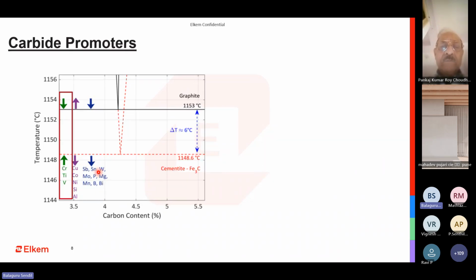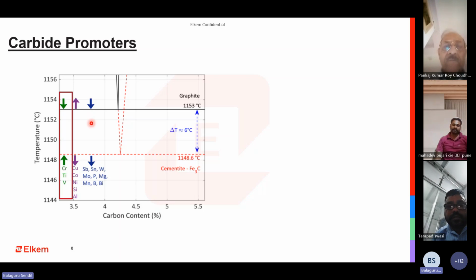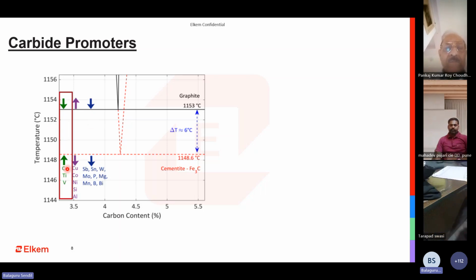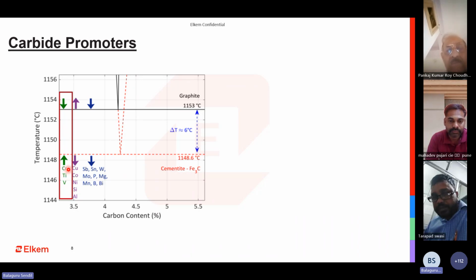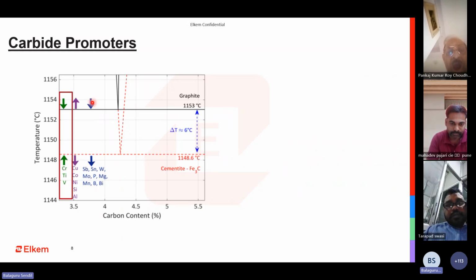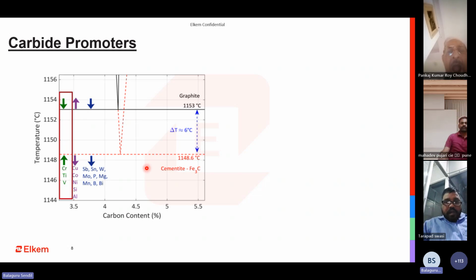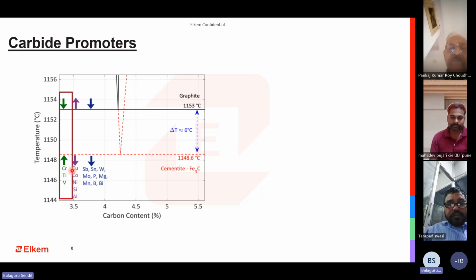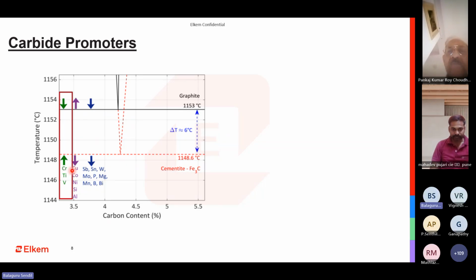But unfortunately, the next one we are picking is carbides. As I told, carbides are very hard and brittle, and we would like to have this completely under control. But in the area you can see here, chromium, titanium, vanadium, these are extremely carbide promoting elements. These elements will try to bring this delta T value further low, pushing all your graphite, all your carbon to come out not as graphite, but to go into a metastable state, go into the metastable solidification and become carbides. So these elements are quite dangerous, and I would like to keep all this under control.